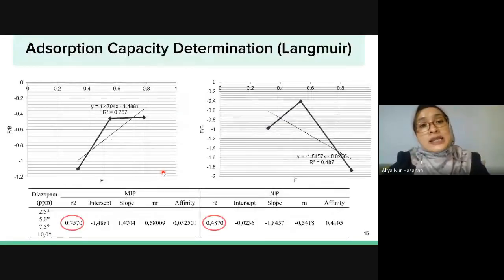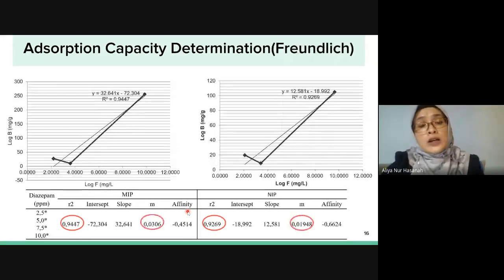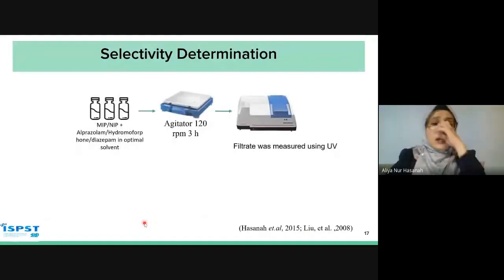This is the result for adsorption capacity determination on Langmuir. We see from the correlation coefficient that it's far from 1, so it means the MIP or NIP doesn't fit with Langmuir, so the adsorption is not monolayer. We continue to fit into the Freundlich, and we see that the correlation coefficient is near to 1, so it means the MIP or NIP has multilayer adsorption and fits with Freundlich, and the capacity of the MIP is larger than NIP. We continue the analytical performance using selectivity determination